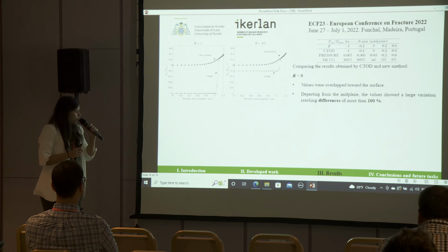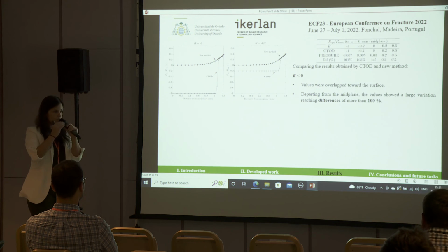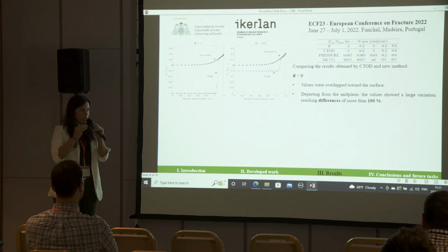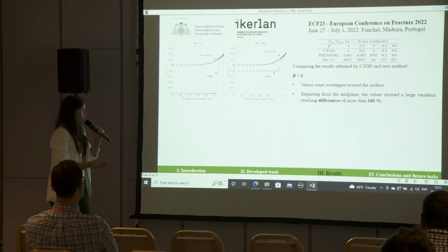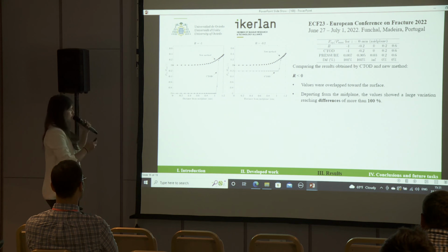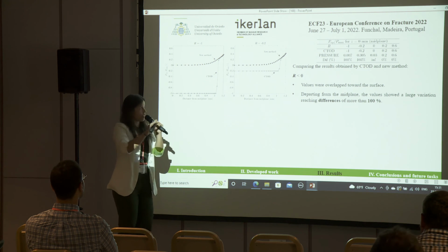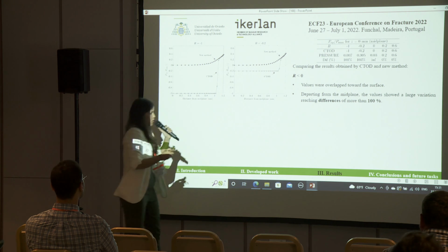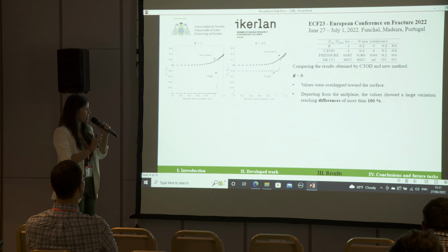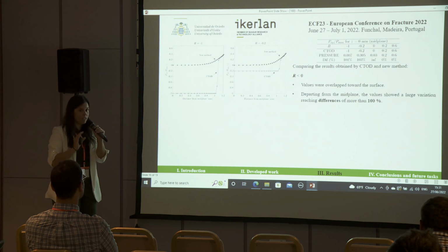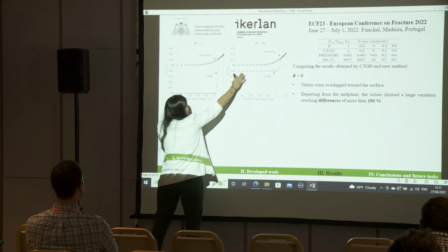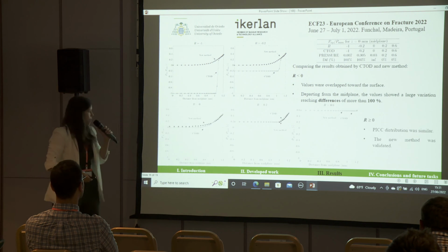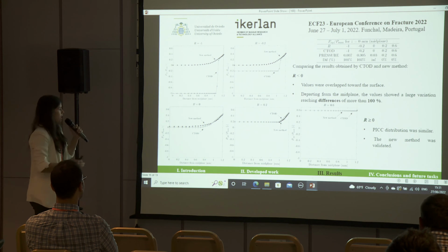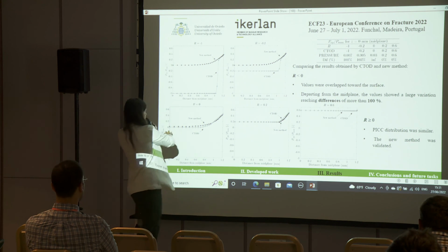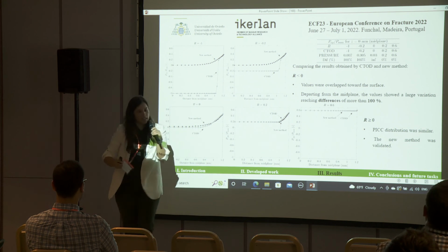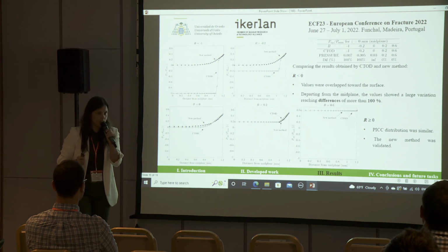Well, to assess the suitability of this new procedure, the results obtained with both methods were compared. Focusing on the negative stress ratios, we see that the values overlapped toward the surface, here and here. And departing from the midplane, the values show a large variation, reaching differences of more than 100% here. And finally, turning to the positive stress ratios, the peak distribution through a thickness was similar for both methods, and it can be stated that the new method was validated.